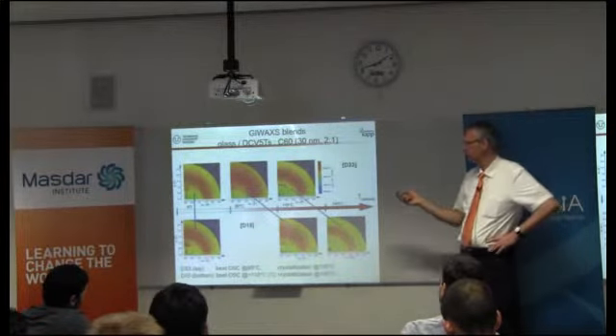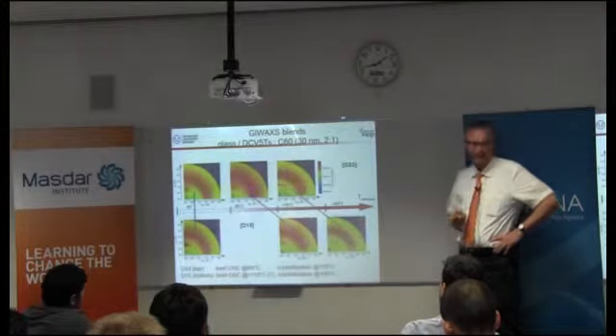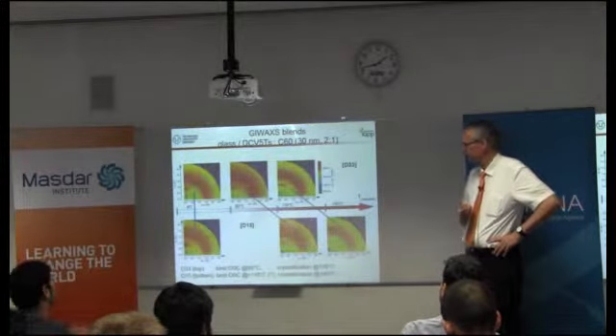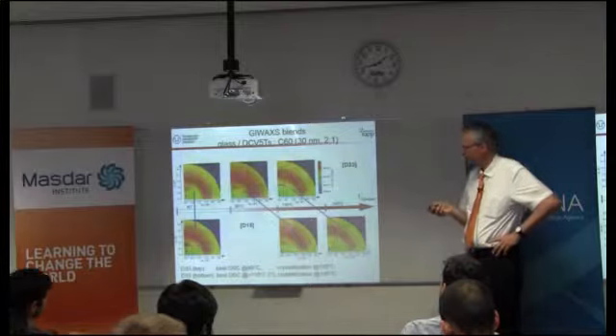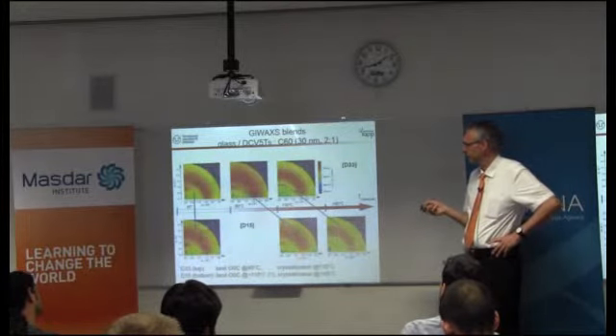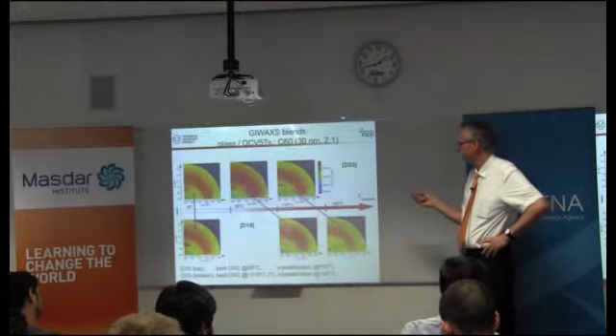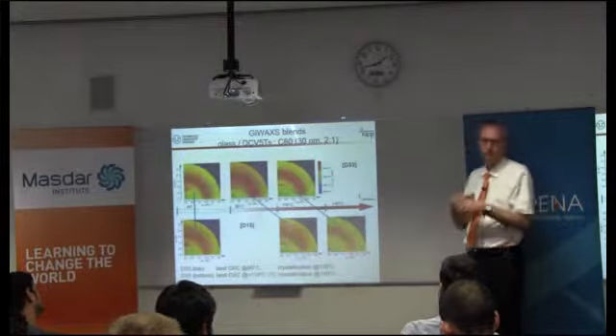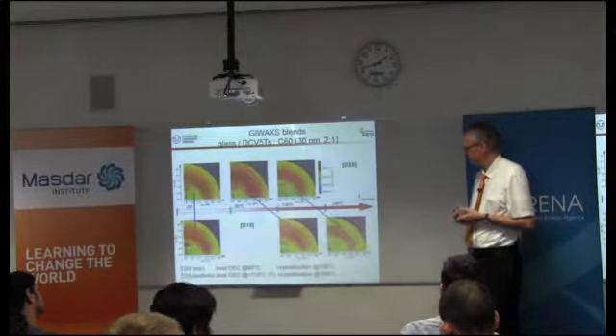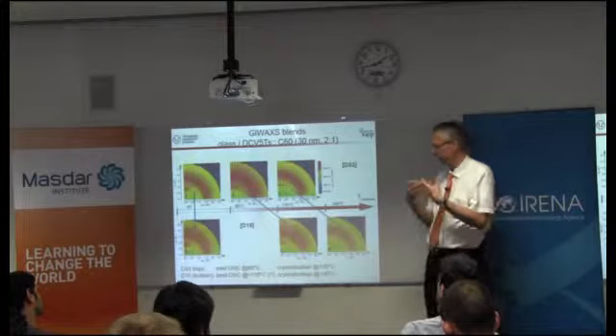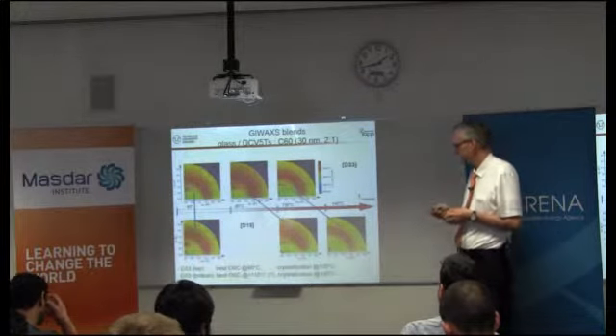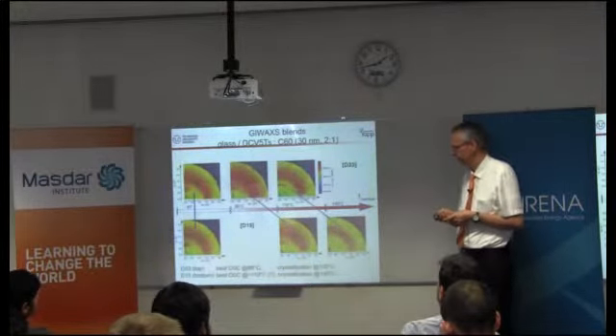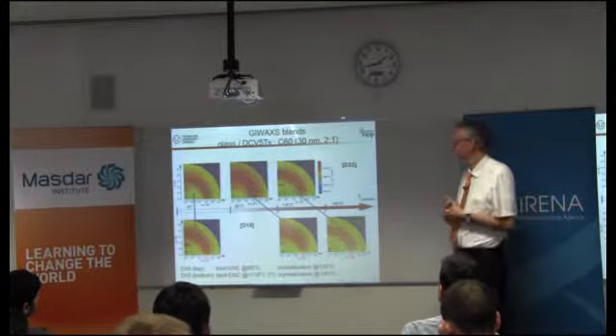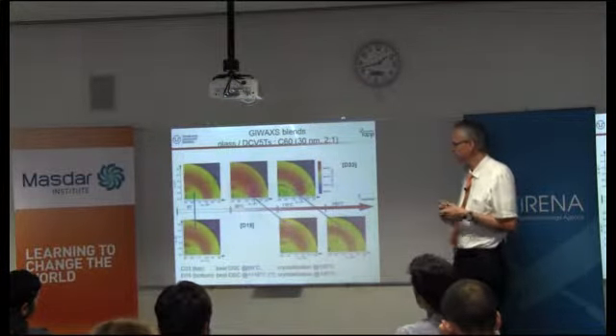However, the solar cells we produce typically at lower temperatures, 90 or so, because of processing reasons. And therefore, the main message was that we concluded this compound to be better only because we were in the wrong temperature range for this other compound. And if you go high enough in temperature, even this compound can pack very well and produce very good solar cells. By that I want to show you how complicated this business is.